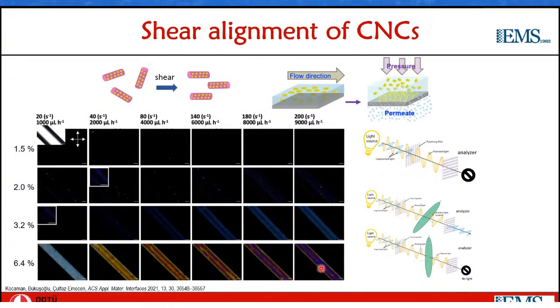So what we wanted to make use of is these stable sols, and some interesting properties of these sols, to make them into a membrane. Cellulose nanocrystals show liquid crystalline behavior. After a certain concentration in aqueous suspensions, they assemble into what's called the chiral nematic phase, which I will show in a few slides later. But what we're more interested in is that they align into what's called the nematic phase of liquid crystals when under shear.